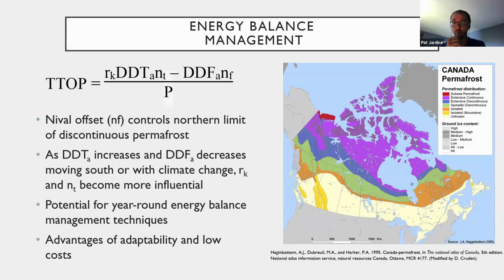So for a really extreme example, at the southern limit of discontinuous permafrost, permafrost might only be found on north-facing shaded slopes in peat bogs that are covered by thin snow cover. And if that's the case, if we're to recreate those conditions on the embankment shoulder by planting a layer of peat moss, compacting the snow during the winter, covering the shoulder with a tarp, and maybe watering the tarp on hot days, theoretically, we should be able to lower ground temperatures just as much and stabilize permafrost under an embankment that has the same air temperature. It's obviously an extreme example, and in reality, it would become ineffective well before that point.